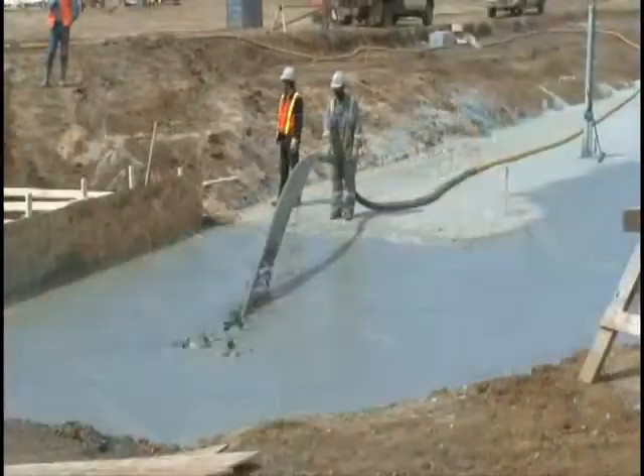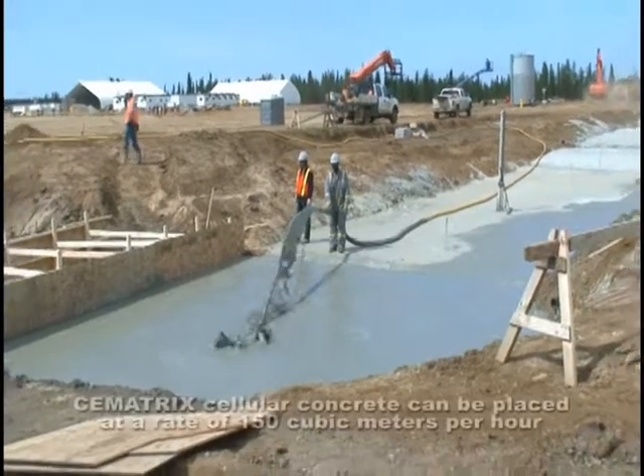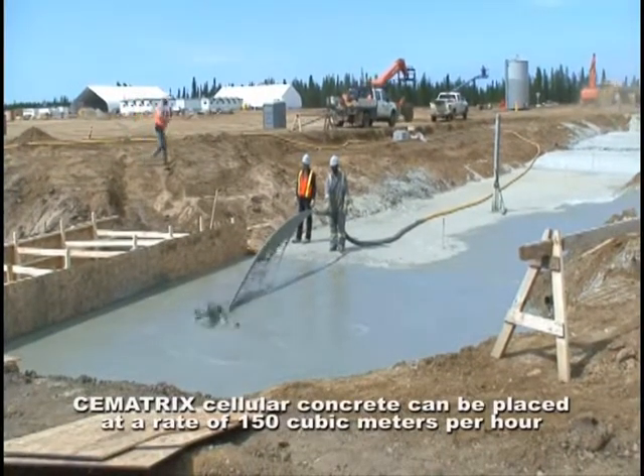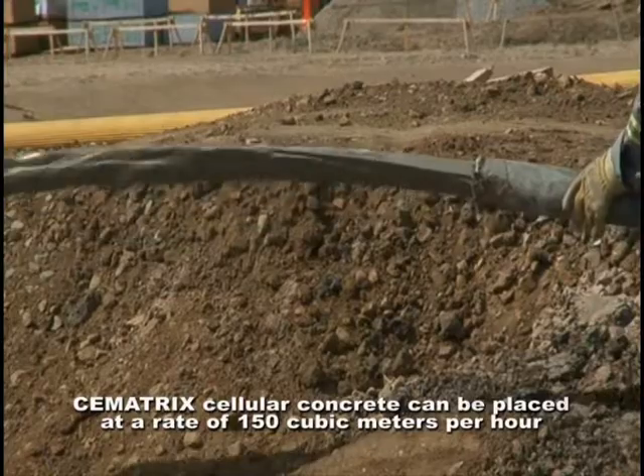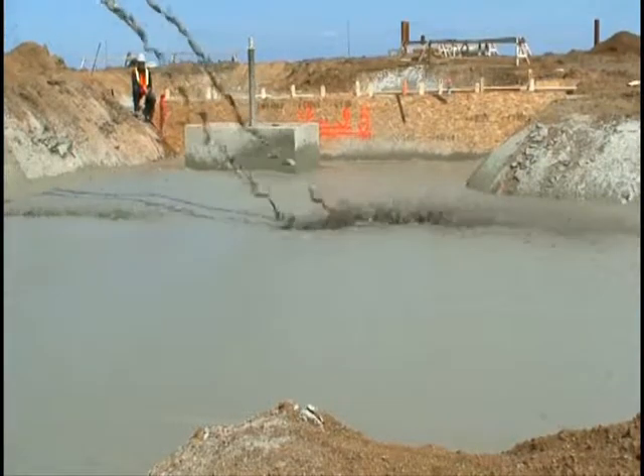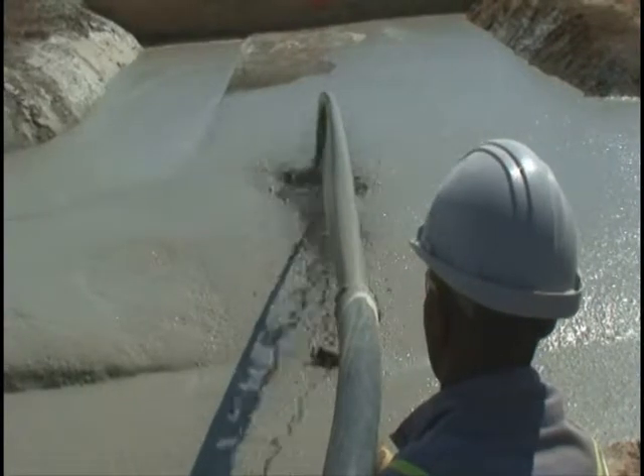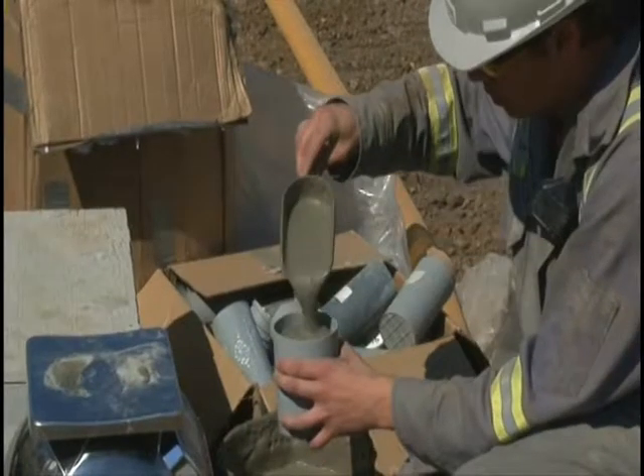Fresh cellular concrete is extremely fluid and is typically pumped and placed through hoses, allowing flexibility in setup and placement locations. CEMATRIX cellular concrete may be produced and placed at a rate of up to 150 cubic meters per hour, depending on the required density, and pumped up to 1 kilometer from the dry mix batch plant.